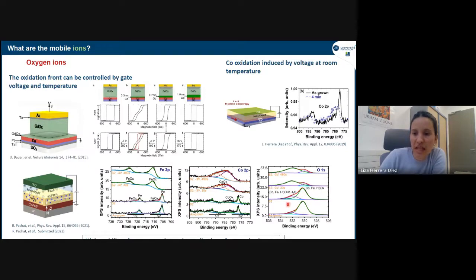So here you see at the beginning, we have a peak that is mostly due to this hafnium oxide that is there at the beginning, which we actually need to have because otherwise the cobalt will be completely oxidized in air. So we need to protect it. And we put hafnium oxide, an oxide that also has high ion mobility. So there is some oxide already in the layer, and it's here. But then when we switch on the electric field, we see that there is this other oxygen peak here that grows a lot thanks to the electric field.